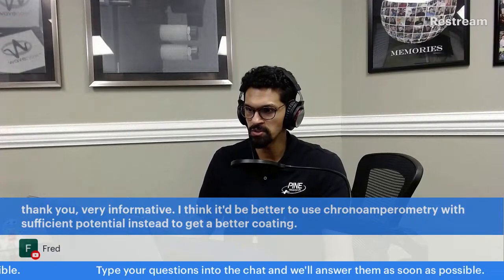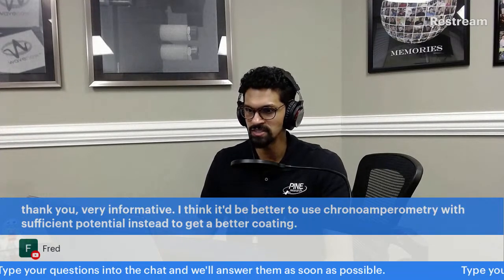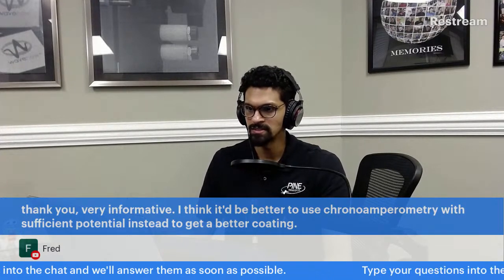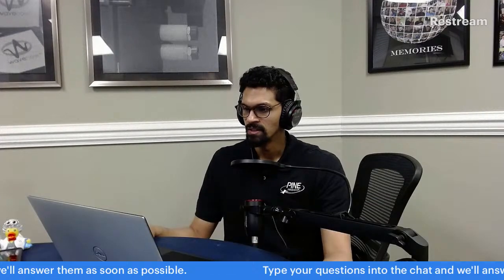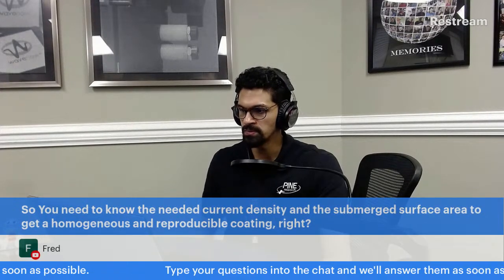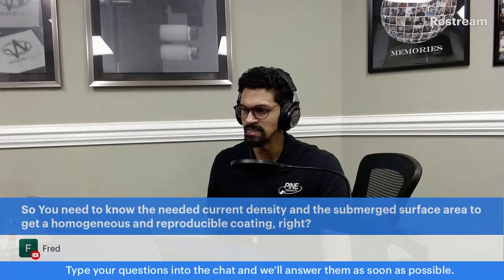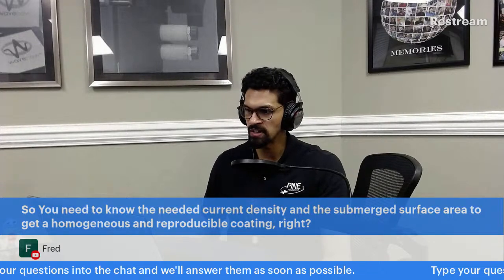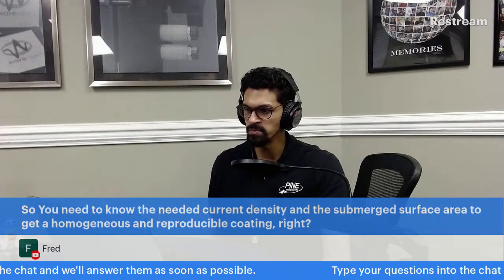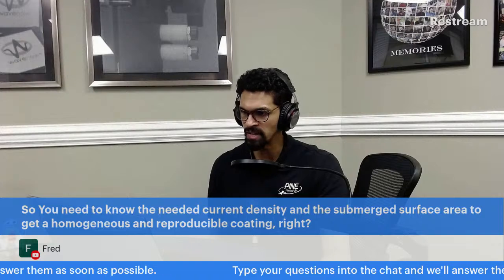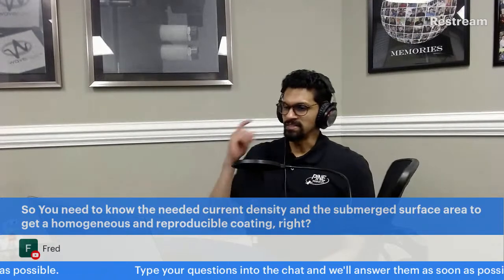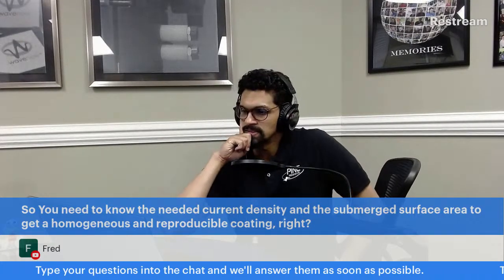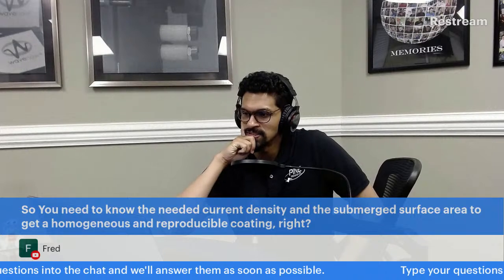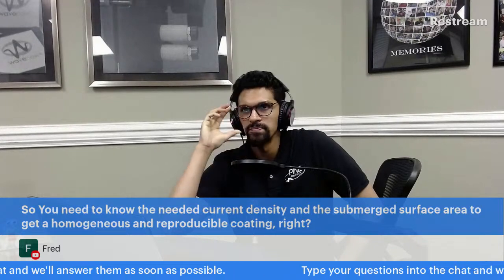I think it'd be better to use chronoamperometry with sufficient potential instead to get better coating. So you need to know the needed current density and the submerged surface area to get a homogeneous and reproducible coating." Correct. Right. So you need to know the current density, submerged surface to get a homogeneous coating.